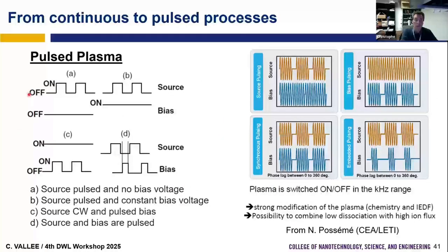So usually when we have an HDP source or a dual frequency process and we want to pulse, we have different ways of pulsing. For example, we can only pulse the source and not pulse the bias. The bias can be continuous. Or we can pulse the bias and not pulse the source. Or we can pulse both the source, so the power applied to the coil for the HDP, and the power applied to the bias. When we pulse, we can pulse synchronously, or asynchronously, so we can have some delay between them.